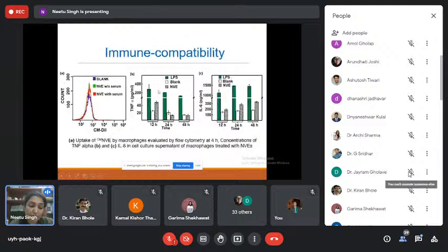Because it is derived from blood, we thought of looking at the immune response to it, and we found that TNF alpha is a marker for immune response, whether your immune system has recognized it or not. We found that the immune system does recognize it in the early time points, like 12 hours. However, it subsides down and becomes more self-like after around 48 hours.